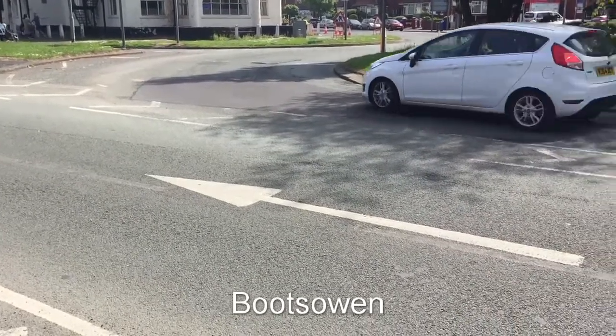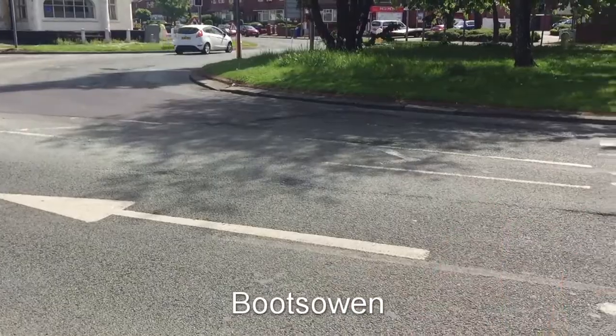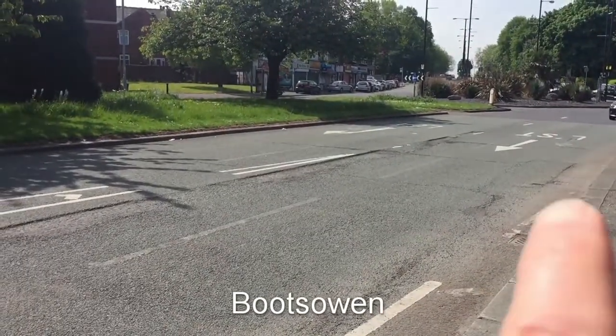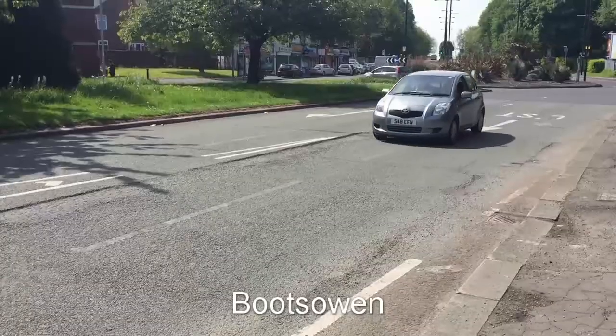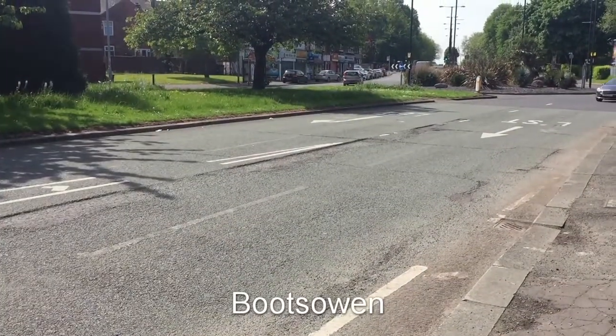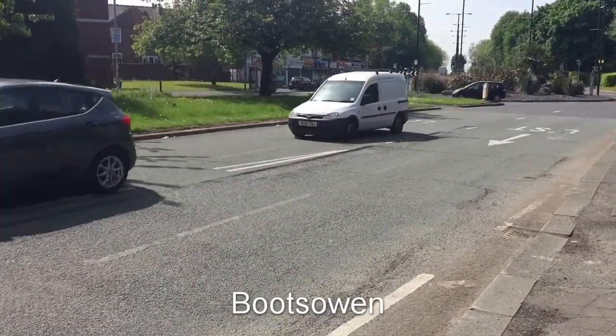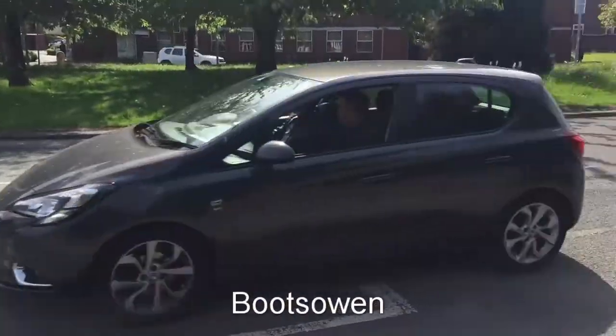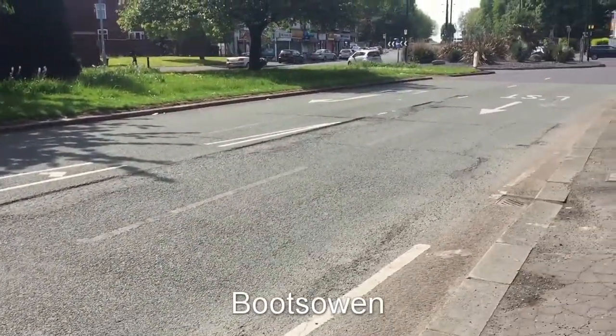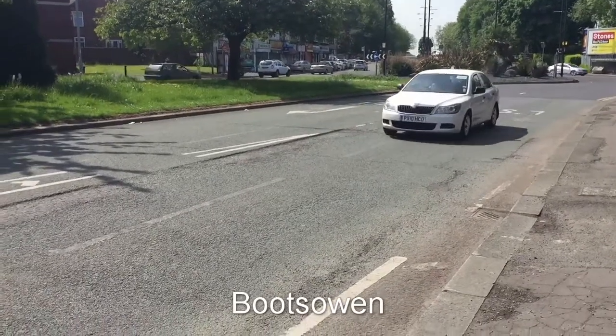So there really isn't much of a solution at this location, other than to continue to replace it. But bizarrely at this roundabout, everything beyond that line — around this roundabout and up the other side — has been replaced with hot rolled asphalt, which will provide durability to resist the action of traffic undertaking maneuvers in this type of situation. Why it wasn't done on this stretch is probably because at the time that was replaced, this section here hadn't failed.